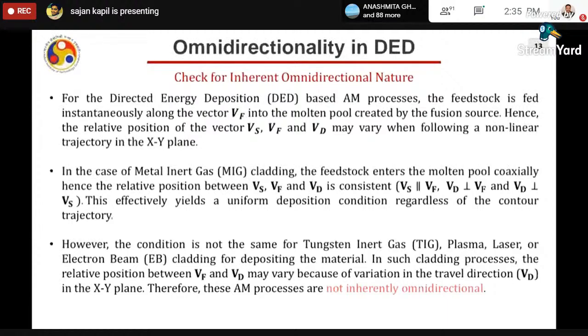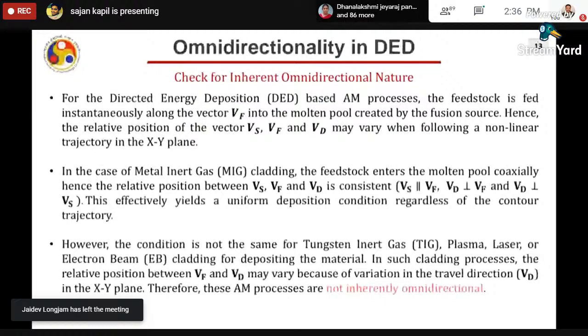However, the condition is not the same when you use tungsten inert gas welding, or plasma welding, or laser welding, or electron beam welding, or cladding. In that case, VS and VF come from two different sources. The source itself is not the feedstock, like in the MIG welding case, where the wire was itself creating the arc. In this case, when we use non-consumable electrode type of thing like tungsten inert gas, plasma, laser, or electron beam, the source is separate, and in the molten pool created by the source, we feed the wire or powder. And hence, it may happen that these three vectors may not remain consistent throughout the process when we deposit on a non-linear trajectory, and hence the process is not inherently omnidirectional. So we have to make it omnidirectional.